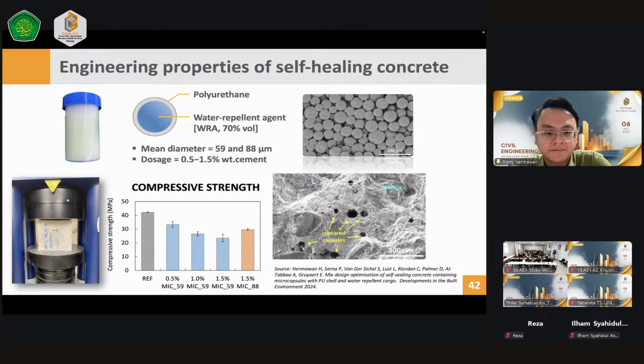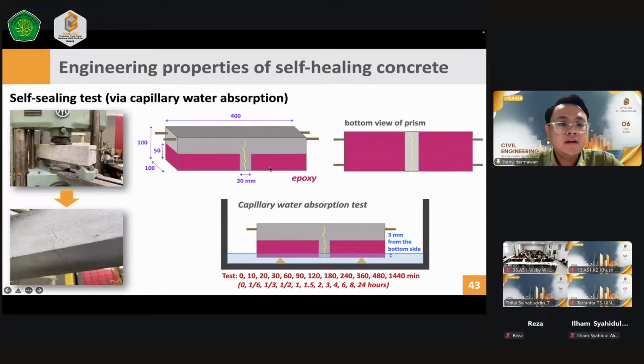So this is one of the reasons why the use of the capsules reduces the compressive strength. But when we are designing self-healing concrete, we should not only focus on the strength itself. We should also look at another side. What will be the benefit of using the microcapsules? In order to confirm the sealing ability of the capsules, we can also design prisms. At the time, I designed prisms, put epoxy on the bottom layer of the concrete, and the specimen was cracked, and then I performed a test called capillary water absorption.